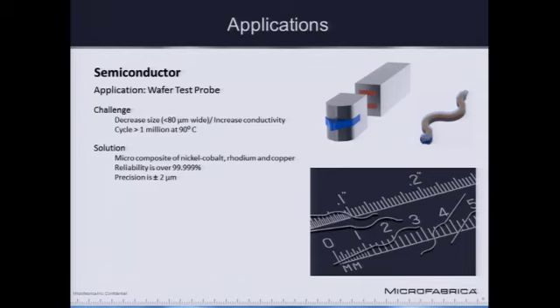But the features are plus or minus 1 to 2 microns, so they're very precise. But it also has a composite set of materials. So we use 3 materials to make this little micro spring. The first material is a nickel cobalt alloy, and this provides the strength. So this provides the outside shell, makes it very strong and mechanical.